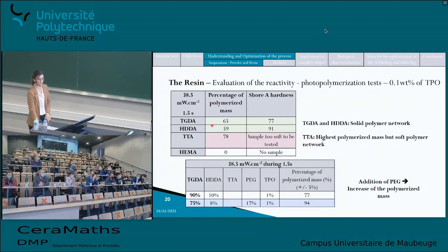However, I also measured the hardness of the photopolymerized sample, and I realized that the samples produced with the TTA were too soft to be tested. So the TGDA and the HDDA provided a solid photopolymer network, whereas the TTA had the highest photopolymerized mass, but provided a soft photopolymer network. I also did another experiment where I mixed the TGDA and the HDDA alone, and then where I added some polyethylene glycol 200. And what I obtained was that the addition of polyethylene glycol 200 seemed to increase the photopolymerized mass, the percentage of polymerized mass.